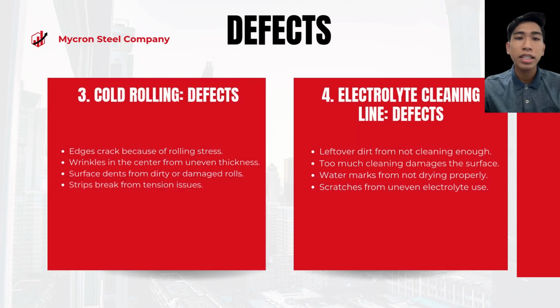In the cold rolling stage, excessive rolling stress can cause cracks along the edge, leading to product rejection. Uneven thickness distribution may create wrinkles in the center of the strip. Additionally, surface dents can occur if rolls are dirty or damaged, compromising product quality. In extreme cases, improper tension control can cause the metal strips to break, leading to material waste or production delays.